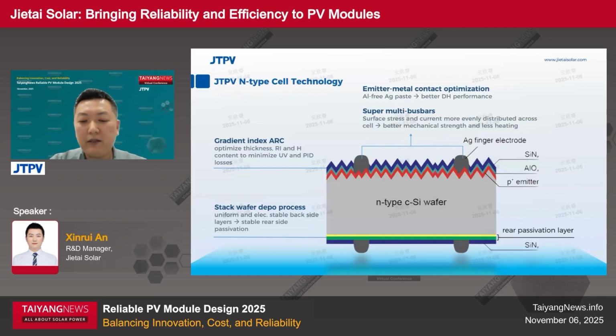And the emitter metal contact optimization uses less corrosive silver paste, free of aluminum, to not only reduce metal-induced damage, but also enable better DH for the cell. And in addition, the surface stress and the current are more evenly distributed across the cell with our super multi-busbar structure, leading to better mechanical strength and less heating of the cell.